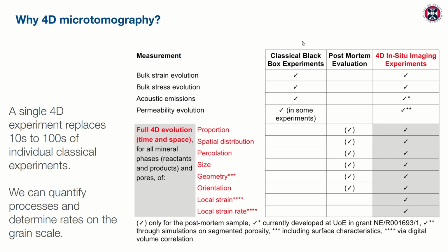I call them black box experiments because despite rock deformation experiments, of course, have advanced substantially over the past century, actually, they are still somewhat limited by the fact that we cannot actually observe the sample, right? That we can only indirectly observe and monitor the sample, and as such we can determine the bulk strain evolution, for example, the bulk stress evolution. We can use acoustic emissions to monitor processes in the sample, even do tomography with that, but it's relatively inaccurate. And we can also, of course, say something about the bulk permeability evolution of the sample, right?